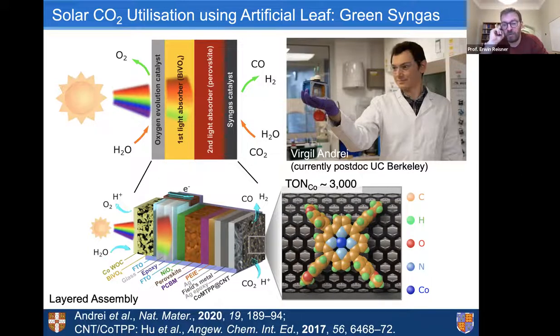So what we do with this device, we just put it on a heat plate. We put the Field's metal on top, heat it up to 80 degrees. And then the Field's metal melts, and you can nicely seal off the entire device. And this temperature is really good because it still does not damage the perovskite. Once you go beyond 120 degrees, it will really start to damage the light absorber. And another advantage of the Field's metal, since it's an alloy, it's conducting. So it allows us to integrate now our molecular catalysts for the CO2 reduction.